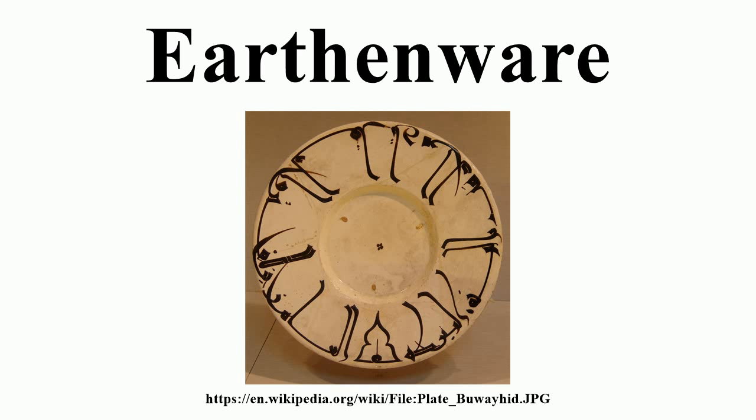Darker-colored earthenwares, typically orange or red, due to a comparatively high content of iron oxide, are widely used for flower pots, tiles and some decorative and ovenwares. Production: a general body formulation for contemporary earthenware is 25% kaolin, 25% ball clay, 35% quartz and 15% feldspar.